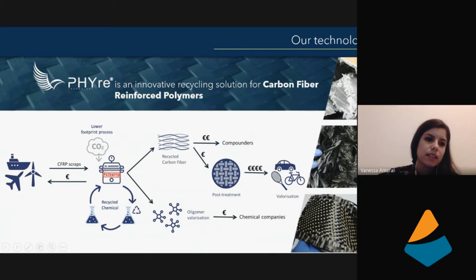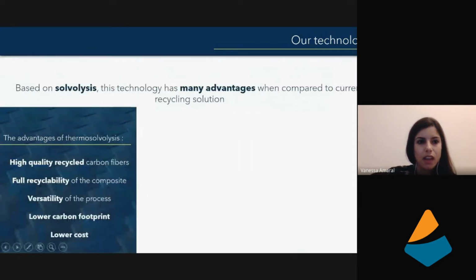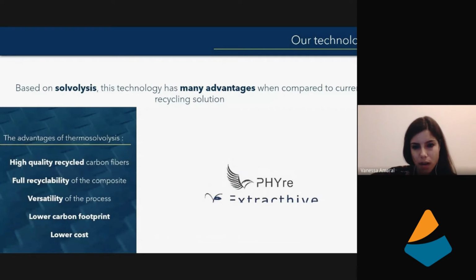So mainly we're going to collect composite scraps. We're going to put them in a large reactor. We're going to put a mix of chemical materials that's going to degrade the matrix of this composite material. We're then going to recover the carbon fibers from one side, and recover the oligomers from another side. The oligomers are today going to be valorized in chemical companies as a byproduct, and the carbon fibers can then be sent directly to compounders if you want a normal valorization of this carbon fiber, where for sure there is a market for this recycled carbon fiber, or we can go for different ways of post-processing in order to go for high value added applications. So I'm just going to show a little video where we can understand a little bit more about the process.